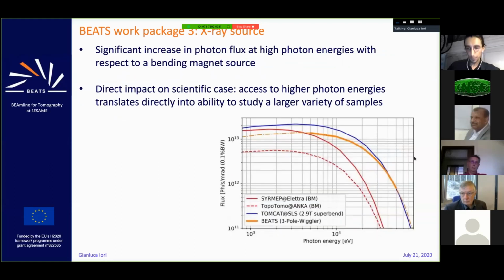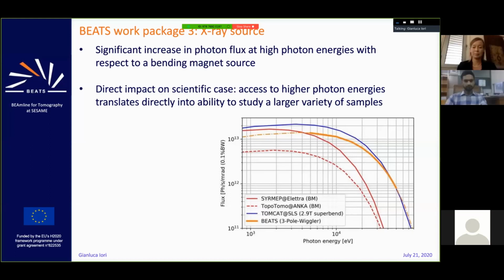And this is a simulation of the flux that we will have. In red, there are 2 beamlines, SYRMEP at Elettra, the Italian synchrotron, and TopoTomo at former ANKA, now the KARA facility at KIT. These are 2 bending magnet imaging or tomography beamlines, and you see that by installing a 3 Tesla 3-pole wiggler, we will reach higher photon energies. In blue, there is a comparison with TOMCAT at the Swiss Light Source, which is the example that we are following. So a significant increase in photon flux at the high photon energies with respect to a bending magnet. And of course, a direct impact on the scientific case, because it allows us to access and study a larger variety of samples.